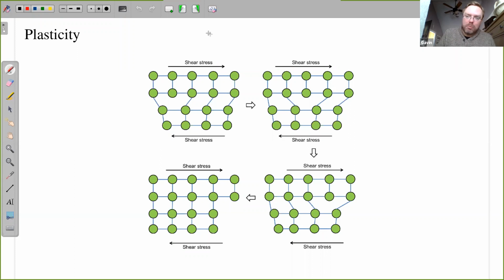And when it comes to adding plasticity, all the approaches I've seen so far have all been along the lines of, well, we've just got to shore this up, right? We've just got to make it so that the plasticity behavior emerges in a way that we prescribe, right? But when you look at the microscopic origins of plasticity and the movement of particles, that breaks down, and that's not something that is being captured, at least to my knowledge, in these lattice models, because these lattice models are usually pretty structured. They're not usually things flowing around.